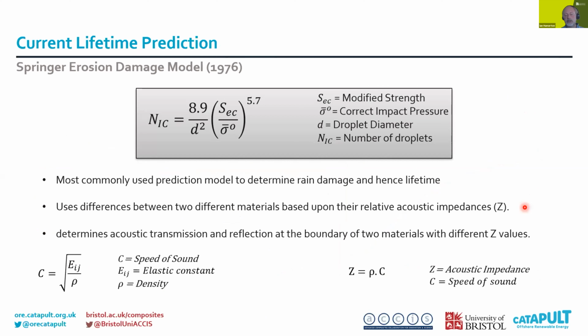It's largely based on changes in material acoustic impedance, because we're talking about the propagation of a wave, which will be transmitted through one material through an interface, a boundary, into a second material. And so the acoustic transmission and reflection behavior will determine how well the energy of impact is dispersed and propagated through the material. And you can see here this is how the speed of sound is calculated.